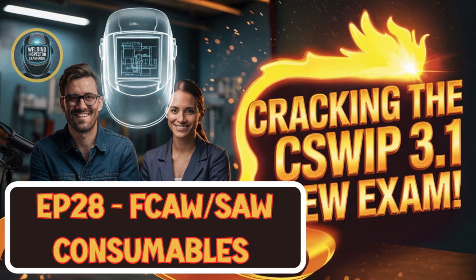Now, in contrast, you have agglomerated fluxes. They're made quite differently. Think more like making a pelletized animal feed or a granular fertilizer. Powdered components are dry mixed, then they're bonded together with some kind of binder like sodium silicate or potassium silicate. They're pelletized and then baked at a much lower temperature, significantly less than the 1,000 degrees Celsius. Then they're broken up and screened. These granules are typically dull, generally roundish, and they are friable. Friable meaning they're easily crushed in your hand, you can crumble them. And they can even be colored for identification.